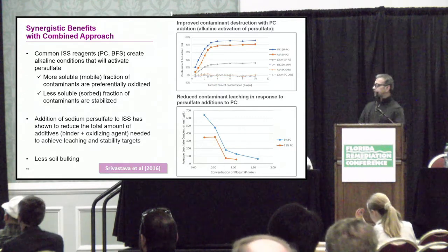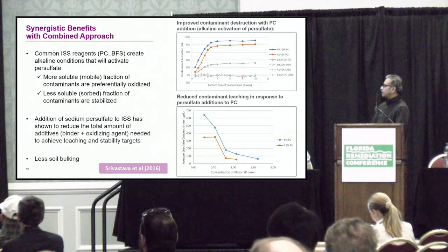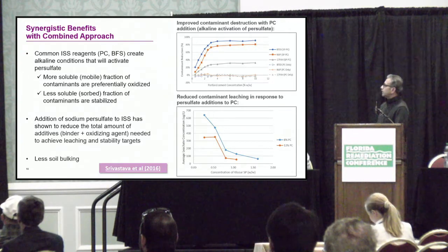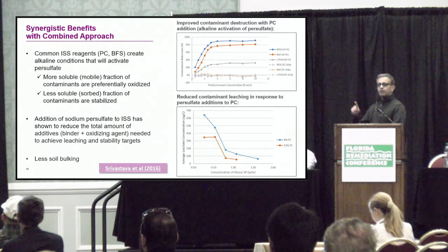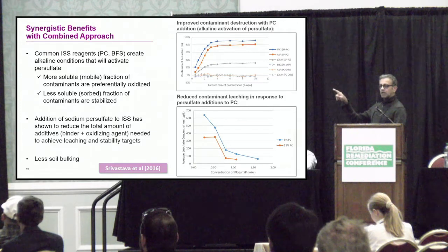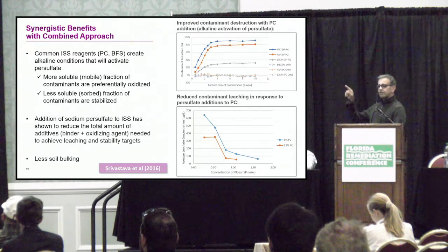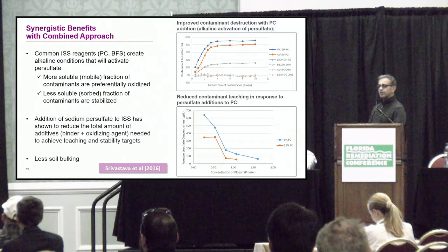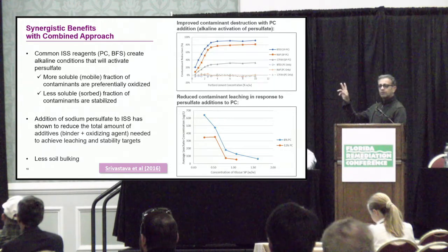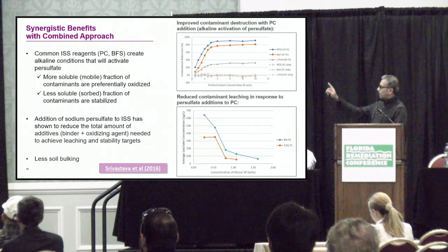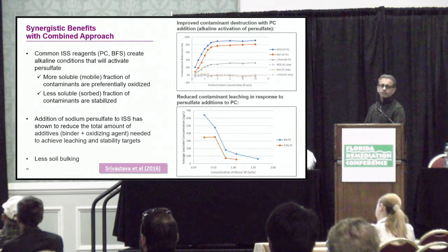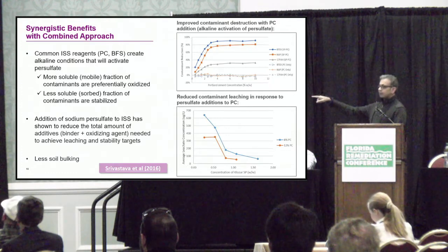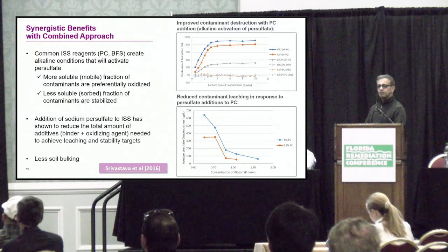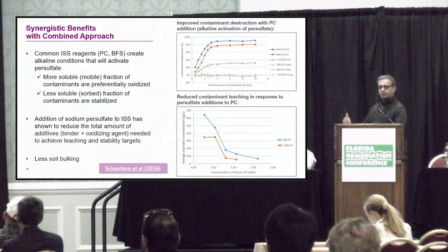So on the chart on top, you can see the data for BTEX, naphthalene, and 17 PAHs. The blue line is for BTEX, the red line is for naphthalene, and the gray line is for the PAHs. The solid lines are the ones where persulfate was added to the mix. The dotted lines at the bottom are where only ISS was used. The chart demonstrates the percentage reduction in the contaminant concentrations in the two cases. So it's obvious that where persulfate was added, you get some destruction of the contaminants, whereas the bottom dotted lines show no destruction because it was only the ISS component. And the chart below shows the reduction in the leachate concentration, which is again expected, because if you destroyed some of the contaminants, then you're going to leach even less contaminants as a result.